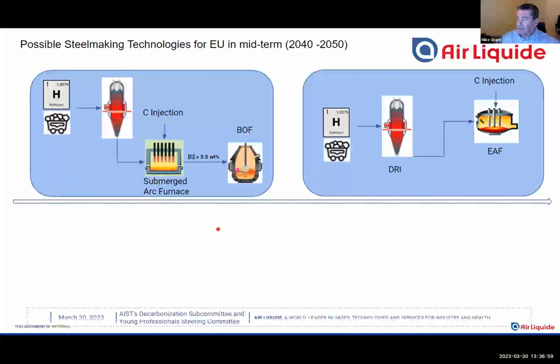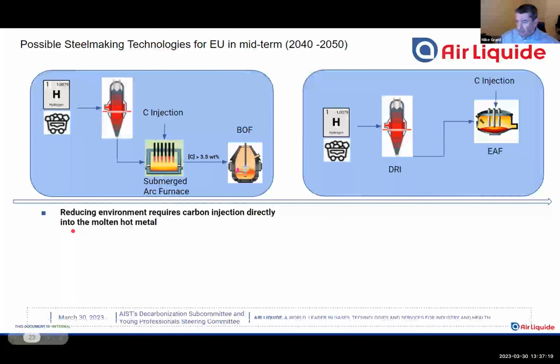So in the future, of course, we want to change this to hydrogen. This is going to produce a DRI with little or no carbon. We'll need carbon injection in both the submerged arc furnace and the electric arc furnace. And so the reducing environment, of course, will require carbon injection. We need to put that directly in the metal, which means it's got to go through the slag and dissolve quickly in the hot metal.